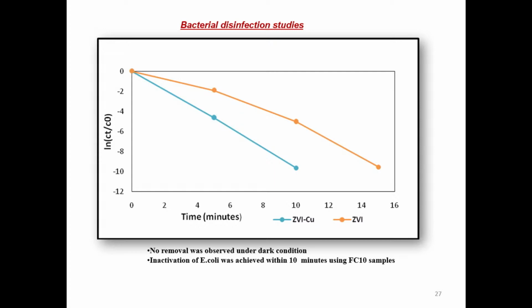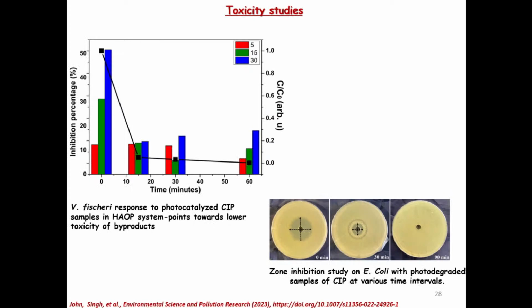So the photo-Fenton process here is responsible and not the material itself. The photo-Fenton process in the presence of your catalyst is responsible for this bacterial disinfection, and with FC10, or the heterostructure, we could see the inactivation of E. coli was achieved within 10 minutes of using these heterostructured samples. Now, the toxicity studies tell us whether the treated water is toxic or not as compared to the untreated water.